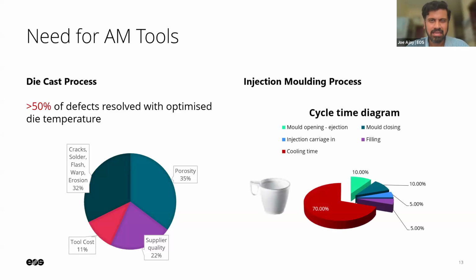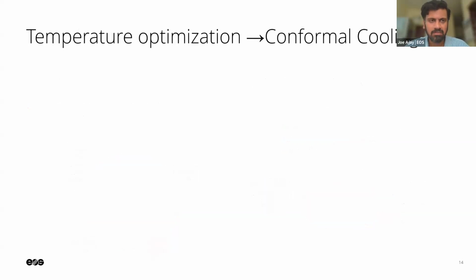And in plastics, the game is a little bit different. We had an assessment along with one of our partners for a cup such as this. And they say in terms of productivity, if we have to increase the volume numbers, because plastic parts go in many more numbers than die-cast parts, the biggest contributor for the non-value-add time is the cooling time, right? So if we have a quick turnaround time or quick cooling time, then we can have a better ROI for our tool. So the solution is, of course, temperature optimization or thermal control, which is offered by conformal cooling.